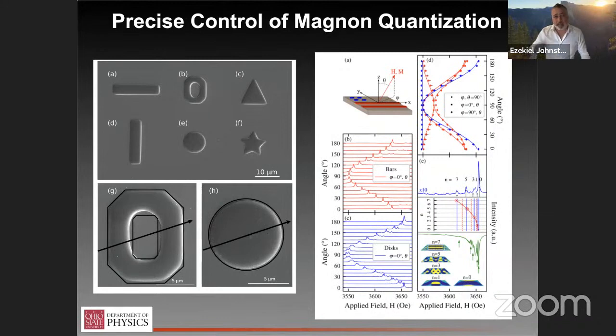It's because it's flat as a function of strain. So in fact, and this is quite surprising, at a guess, it maybe has the same origin as to why we have such low damping despite the lack of long-range structural order at the atomic scale. But straining it doesn't seem to introduce additional damping. And it's not at all clear why that's true.